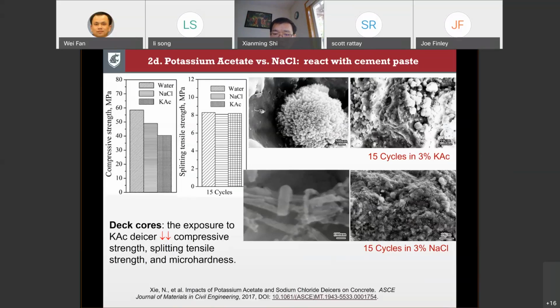Now, depending on the type of deicer we're talking about, the concrete would fail differently. For instance, we simulate this kind of exposure in the lab in an accelerated manner. And at the top, you can see on the left, we're talking about a phenomenon occurring at a very fine scale. If our hair is about 80 microns in diameter, then this is about a 10 micron by 10 micron area. You're seeing some beautiful crystalline phases forming inside the concrete. And with the sodium chloride, you're seeing another type of crystalline phase.